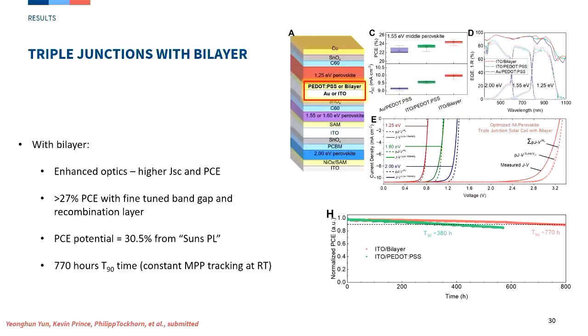What you see is you get a higher current. That's what you expect because you have lower losses, and you also get a very high VOC potential. The JV curve, the electrical measured JV curve is here. This is above 27%, which is very good. But the most striking result here is the stability, which with the new bilayer approach is much higher compared to the PSS, because it's not so acidic, etc.